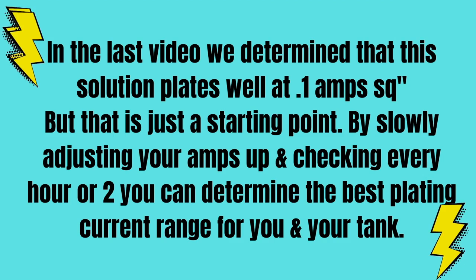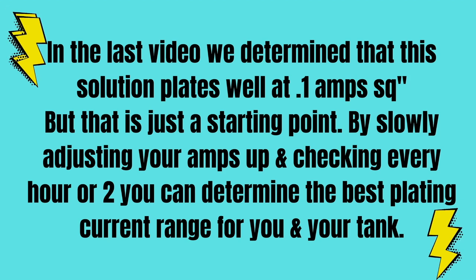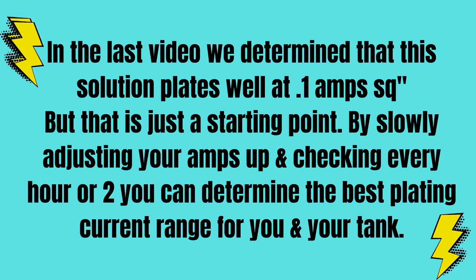In the last video we determined that this solution plates well at 0.1 amps per square inch, but that's just a starting point. By slowly adjusting your amps up and checking every hour or two, you can determine the best plating current range for you and your tank.